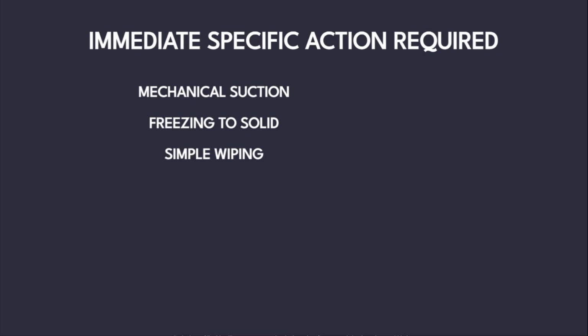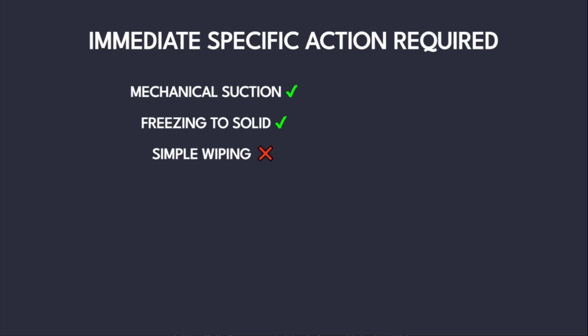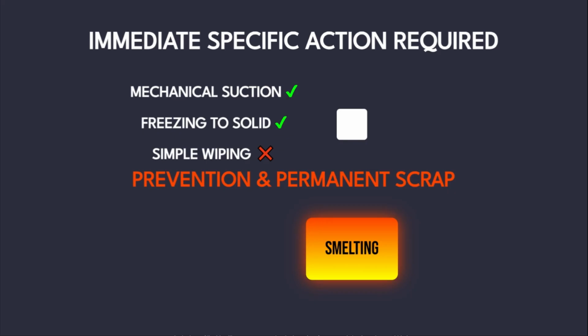Dealing with a gallium spill on aluminum requires immediate and specific action. Because the diffusion process begins the moment contact is made, the liquid gallium must be removed as quickly as possible. Mechanical suction or freezing the gallium to return it to a solid state can slow the damage. However, because the gallium moves beneath the surface oxide layer, simple wiping is often insufficient. In laboratory settings, specialized chelating agents or chemical washes may be used to bind with the gallium atoms, but these are often ineffective once intergranular penetration has reached a significant depth.